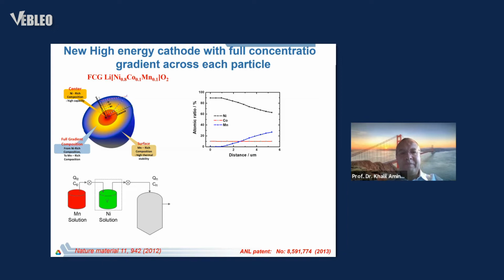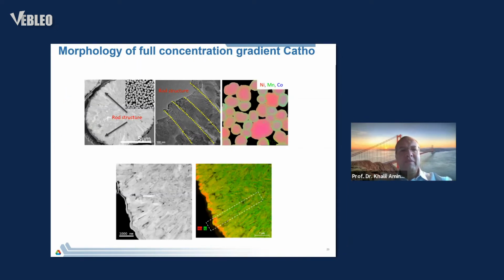This is the morphology of the material. It's very different from the conventional NMC material. It's also spherical, but inside we don't have round-edged primary particles, we have rods. And then if you look at the EDX, you can see that the red is nickel. And then when you start getting to the surface, it becomes green, that's manganese. You can see it also here. It's green, and this is the opposite now. The green is nickel here. It becomes orange because the concentration of manganese increases and the nickel drops. And then when you get to the surface, you have mostly manganese. So you have a very good layer of protection because of the manganese existing at the surface.